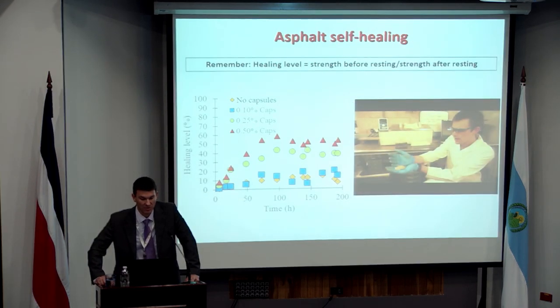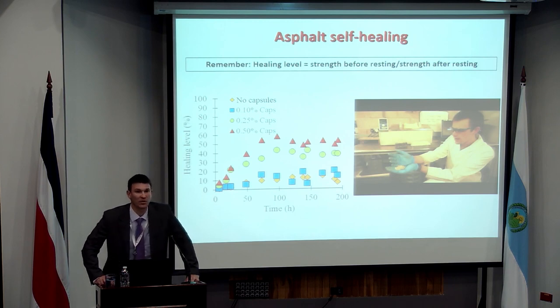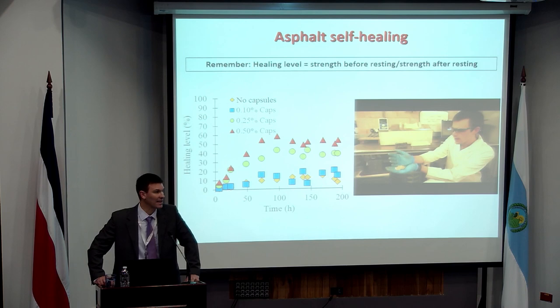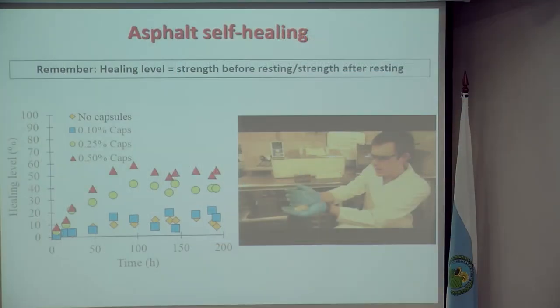How do they work in terms of time? It's not instantaneous. Obviously, that low viscosity fluid needs to locally reduce the viscosity of the binder, which needs to flow then before it can actually do any kind of self-healing. So there is a time effect. There is also an effect, obviously, of the amount of capsules you have in the material. So we've gone up to about 0.5% by mass, which tends to give you your highest amounts of healing.